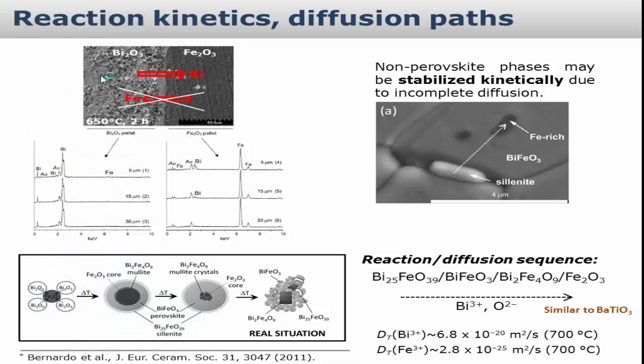The second thing, besides these impurities, is kinetics. So this is BiFeO3, this is now well known. Basically, there was a diffusion couple study done by Bernardo and co-workers. They showed that bismuth diffuses faster than iron, so basically there is a diffusion of bismuth and oxygen toward the iron-rich core. This is the reaction sequence: the sillenite phase is formed, and then the iron-rich phase, and then bismuth should somehow diffuse toward the center to complete the reaction.